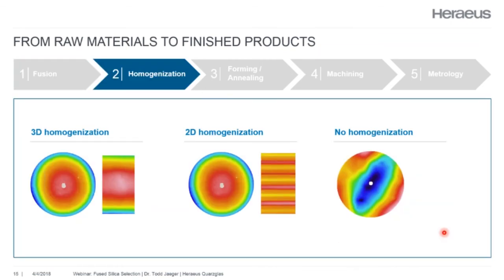The next step for either your quartz or your fused silica is one that's really unique to Heraeus material, and this is the homogenization. The goal of this step is to remove variances in the refractive index. On the right side, we see an example of a material that we would say is as produced, without any additional homogenization. And so you can see that there's a gradient of the refractive index within this interferogram that we're looking at.